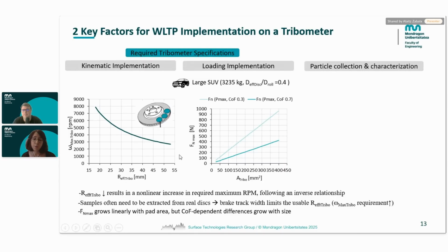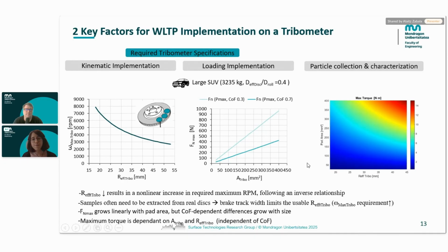Regarding the maximum normal force required, this will depend on the coefficient of friction of the tribo system under test. As we can see, there is a linear increase depending on the area. The differences between both coefficients of friction tend to get bigger for bigger areas. However, considering both cases, the maximum normal force lies below 1 kilonewton. Finally, we have the maximum torque required in the tribometer, which is independent of the coefficient of friction since it depends on the friction force. And we can see the maximum values are below 15 newton meters.